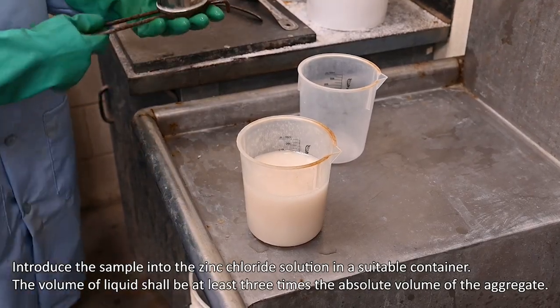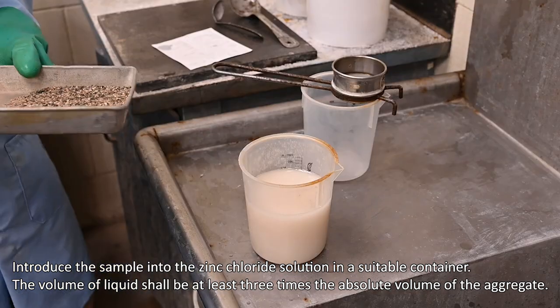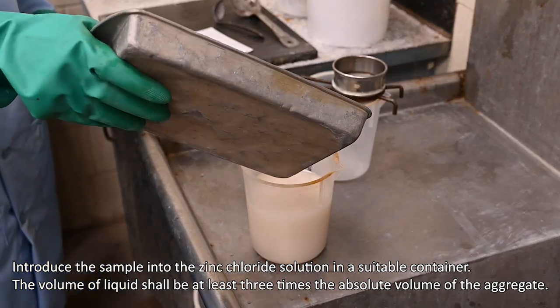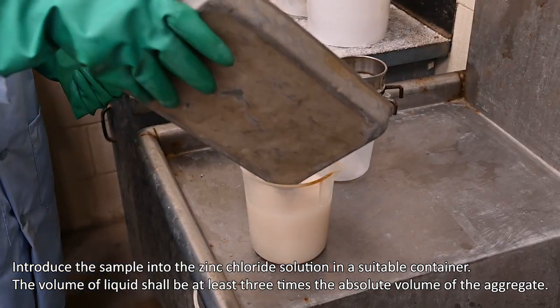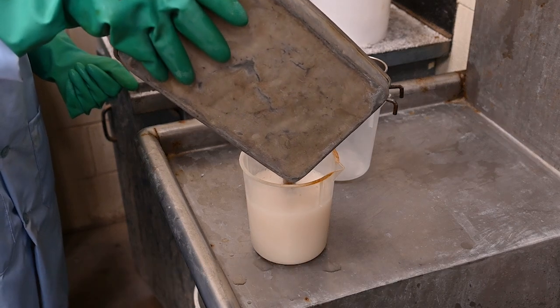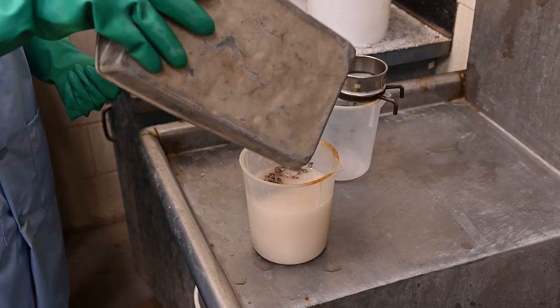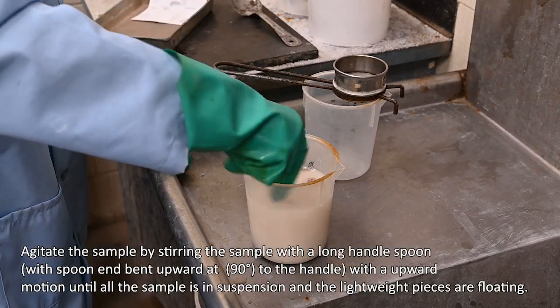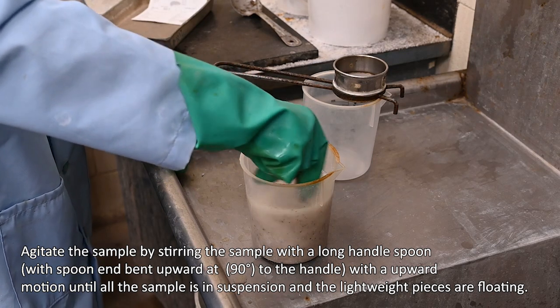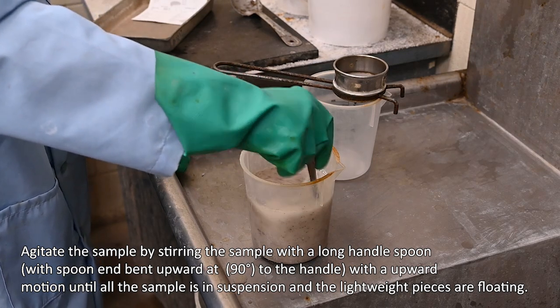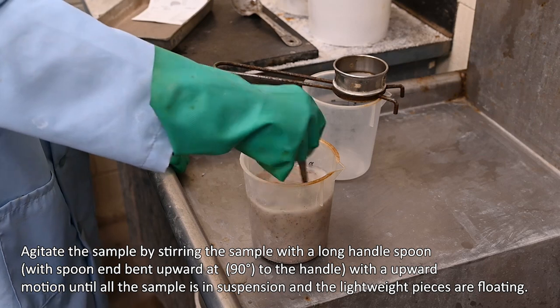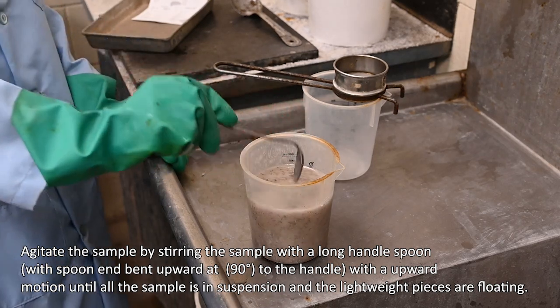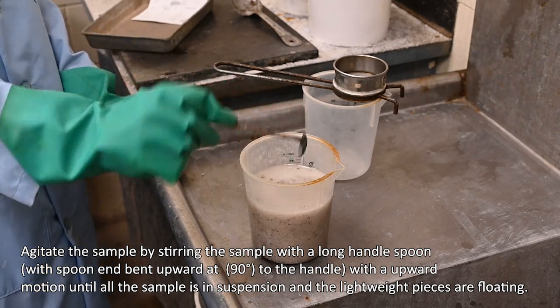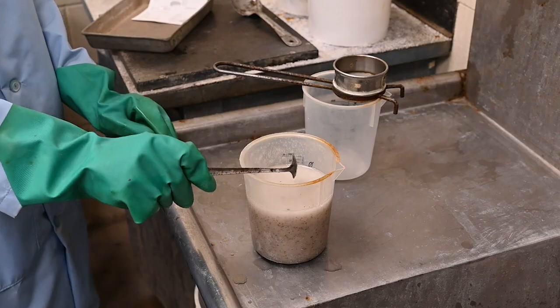Introduce the sample into the zinc chloride solution in a suitable container. The volume of liquid shall be at least 3 times the absolute volume of the aggregate. Agitate the sample by stirring the sample with a long handle spoon, with spoon end bent upward at 90 degrees to the handle, with an upward motion until all the sample is in suspension and the lightweight pieces are floating.